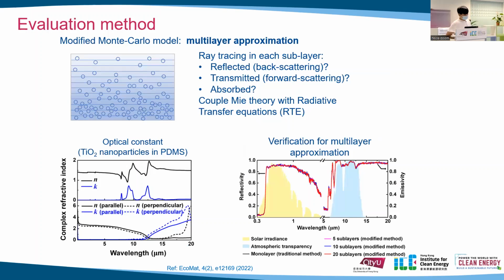And to evaluate the spectral properties, we use a modified Monte Carlo model to see whether it has a higher or lower reflectance. Because the traditional Monte Carlo method is just suitable for a randomly dispersed coating system, we made a multi-layer approximation. We divide the whole coating into several sublayers and make ray tracing in each sublayer. We determine whether the incident ray is reflected, transmitted, or absorbed by coupling the Mie calculation and the radiative transfer equation.